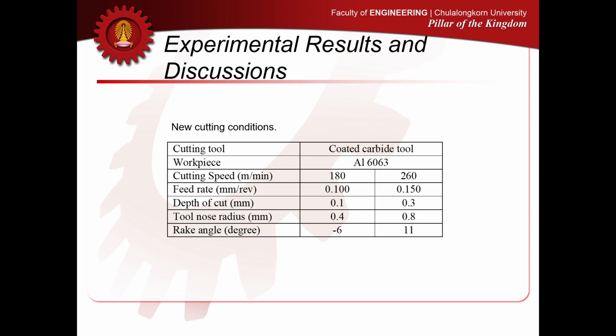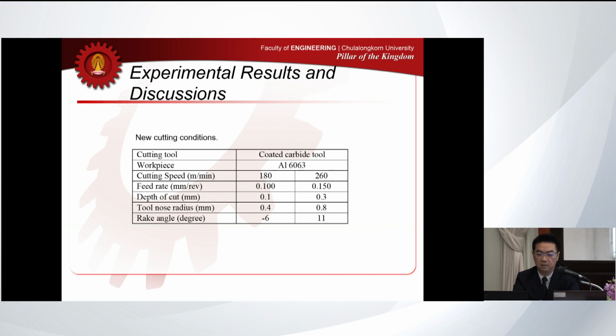This time we also use cutting conditions that are out of the range that we trained it on. We trained it from 150, but now we started from 180 and used 260, to check that the cutting force ratio can help to cut off the effect of the cutting condition or even the hardness. It's just like a dimensionless quantity. The machine can be intelligent and humanless, even though the cutting condition changes, by using the neural network.